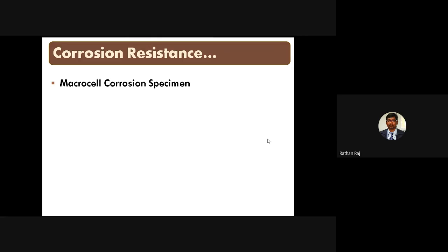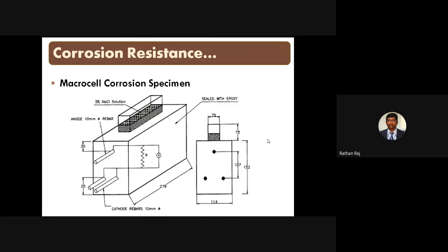One is the macro cell corrosion specimen, which will look like this. For the macro cell corrosion, a concrete beam or rectangular specimen is cast, which has 3 rods. Normally the rod is 10 mm in thickness. One is acting as an anode, and the other 2 are acting as cathodes. These are connected to the potentiostat, and then epoxy resin is applied on the surface of